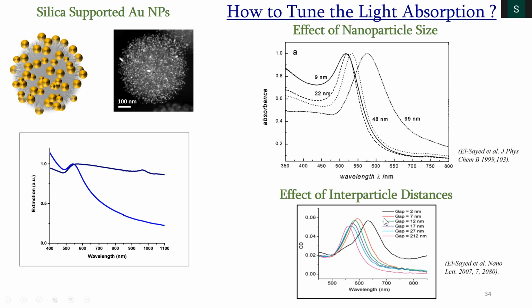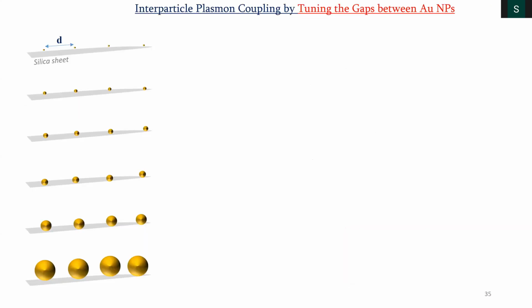Another way is called the interparticle distance, where if you bring the gold particles near to each other, the electron clouds of the gold particles start interacting with each other, and then that entire electron cloud starts to resonate, starts oscillating with the light and has a different resonance wavelength. It's called plasmonic coupling. So we thought of using these two concepts. Even here you do not get the broadband light by either alone, but we thought, can I combine these two and see whether I can get a broadband light absorption? So that's what we did.